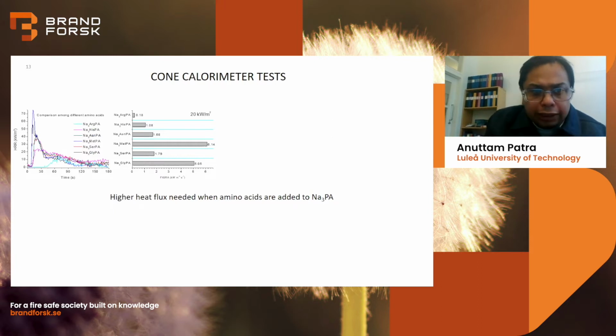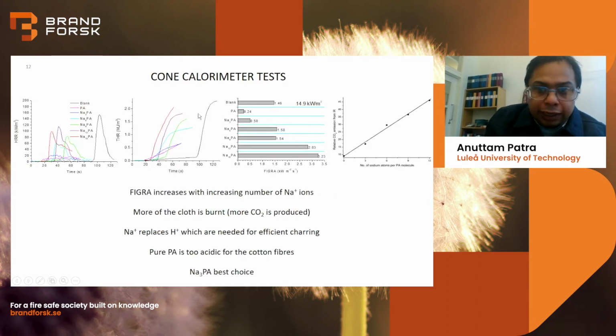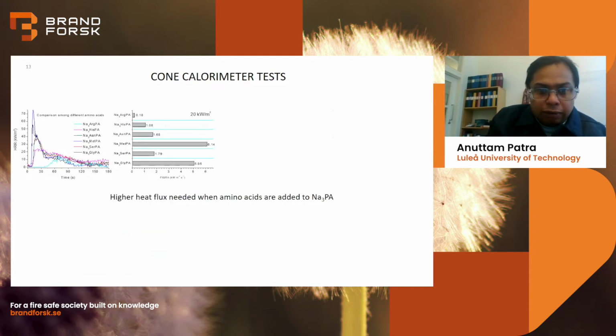Now we move to the next step, which is the actual goal for the project in composition, to try amino acids. We used different amino acids, but the first interesting thing we saw is that these flame retardants can tolerate much higher heat flux. Here we can put 20 kilowatt or more. In the previous one, if we increased more than 14.9 or 15, even the flame retardant treated cloth was burning too fast. But this one can withstand much higher heat flux.